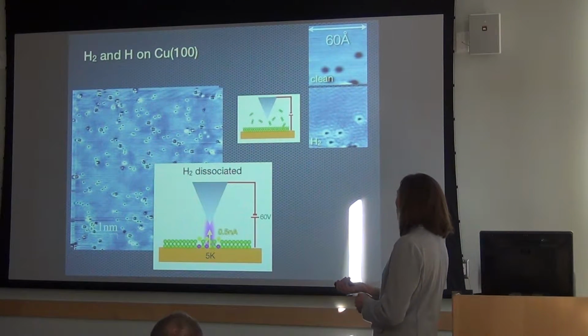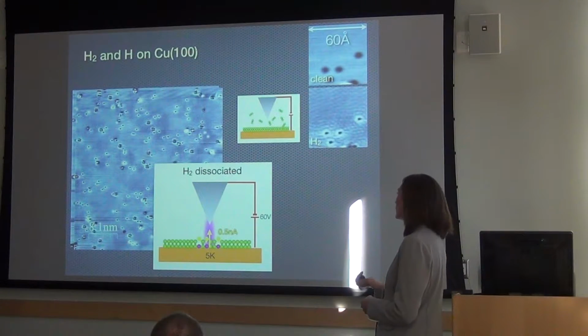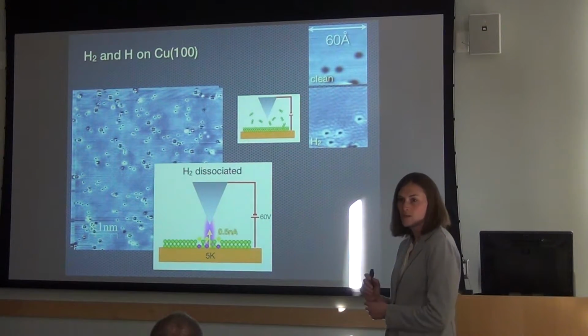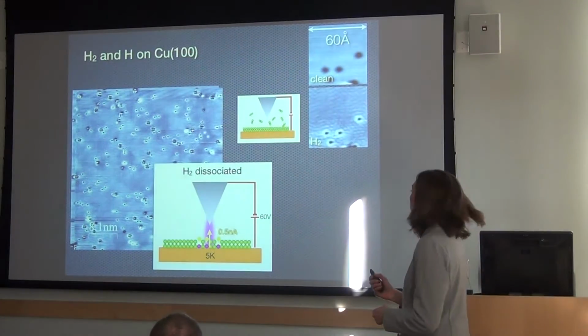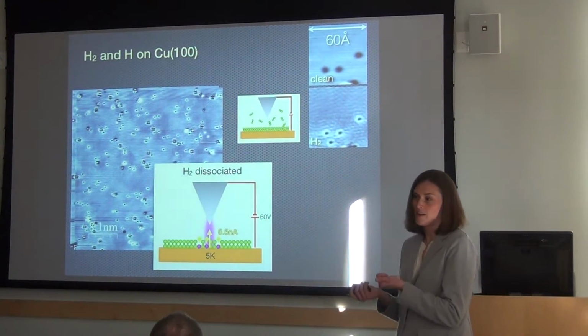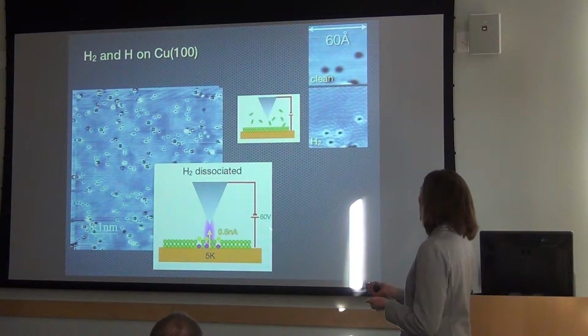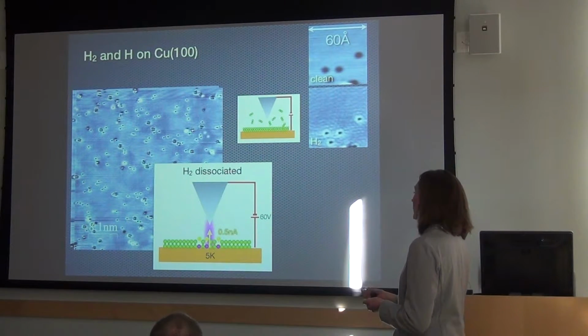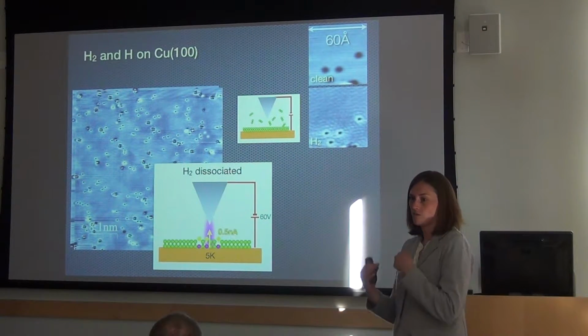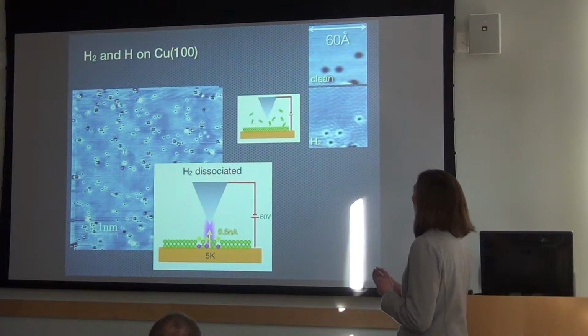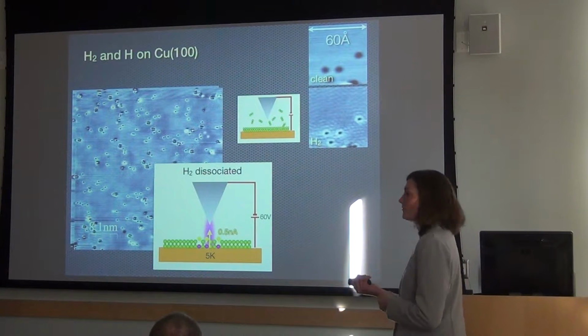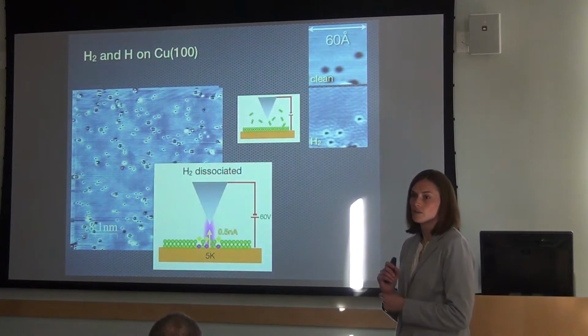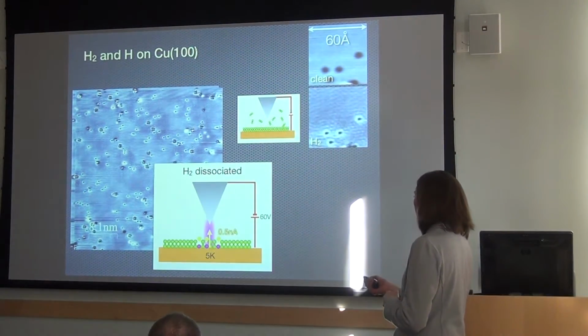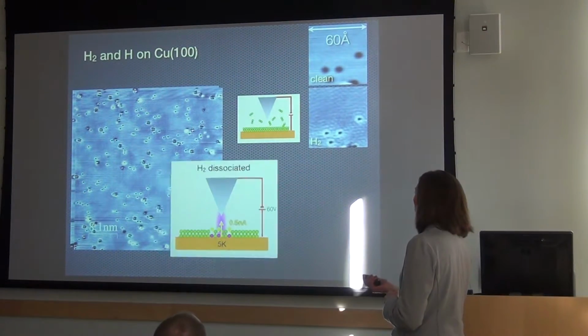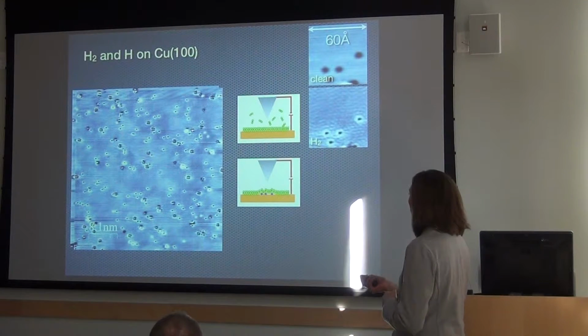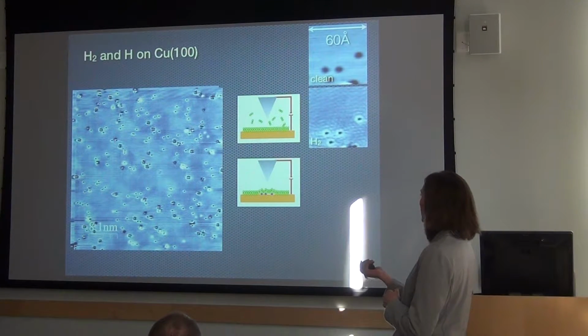So we decided to try to dissociate molecular hydrogen using the STM tip itself. It's a very sharp, pointy thing, and we can apply a high voltage. So we applied about 60 volts with the tip pretty far away from the surface. So this is field emission from the tip to the sample until we got a 0.5 nanoamp field emission current of electrons. And we were able to show that this works. So if you look carefully, when I change the image, you'll see something new.